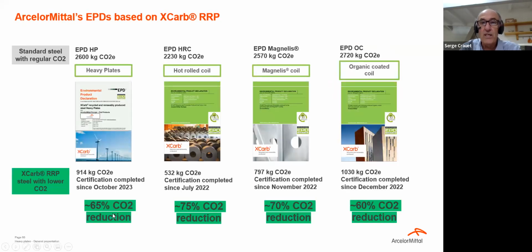Next, please. So here, I told you that I will present you all the flat products about the EPDs. That's a very nice synthesis. You could see with only 1 page where we are. So I told you already about heavy plates, and from 2.6, we will go down to 0.914. You have also, and it's based on the industrial Charleroi slabs, the same for hot rolled coil, and we start with that because the Magnelis and the organic coating are made with this substrate. So Sestao can reach a value of 532 kilos. And the 2.23 is an average of all the plants producing hot rolled coils in flat Europe. And so it's an average value from all the plants.